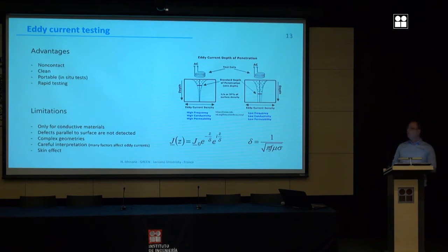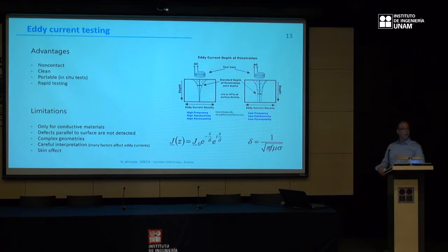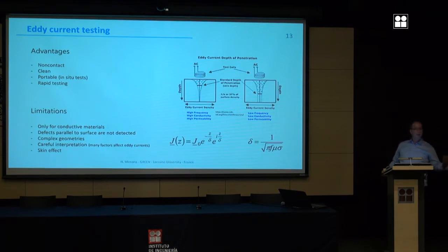You have studied skin effect, eddy current, since we are in frequency domain, alternating current. About 63% of the eddy current flows in the skin depth here, given by this equation. The skin depth is inversely proportional to the conductivity, the permeability, and the frequency. So sometimes, to saturate the material, we can add a static magnetic field, and then go deeper in the tested material.